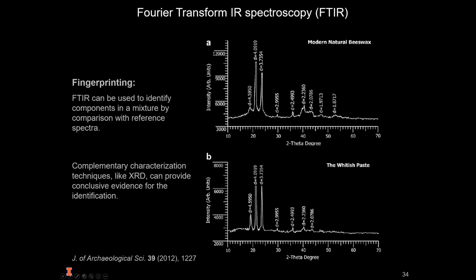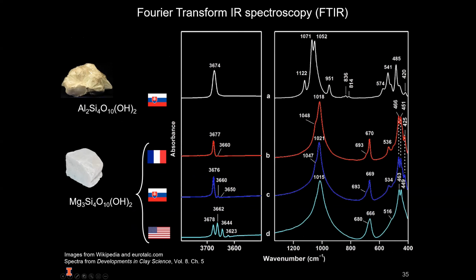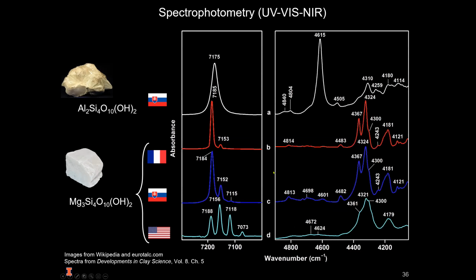FTIR is sensitive to very small changes in the chemical composition of materials, allowing, for example, identification of the source of a sample from small differences in composition, say where a mineral is coming from different origins. In this case, the authors also used near-infrared spectrophotometry as a complementary technique to fully characterize the samples. These differences that we see on the three top samples are mainly due to the presence of a small amount of iron on them.